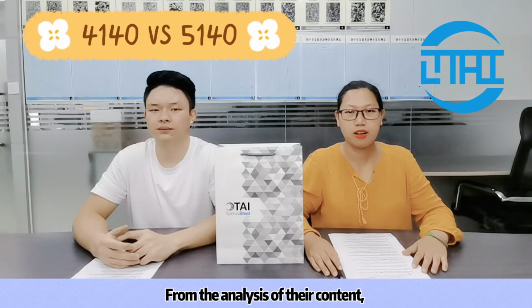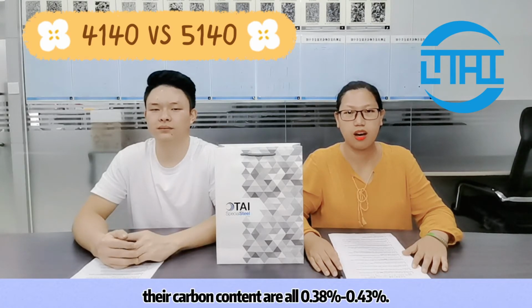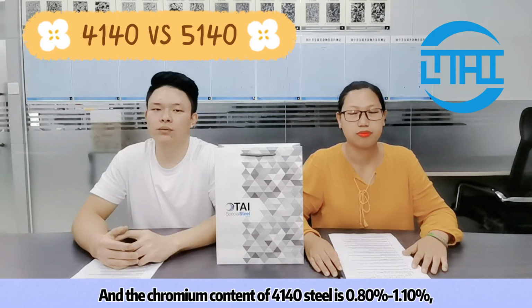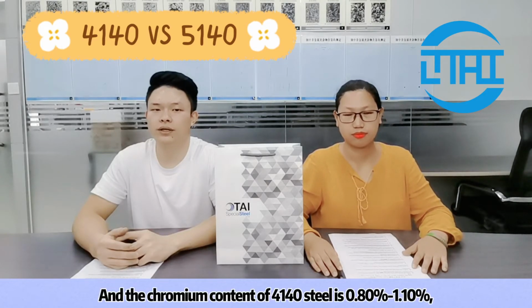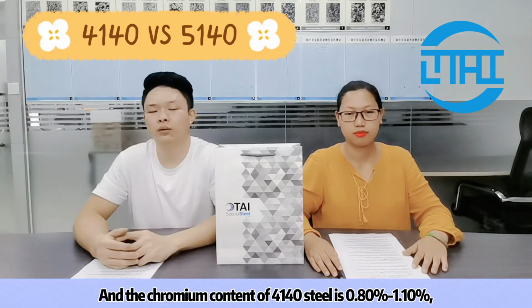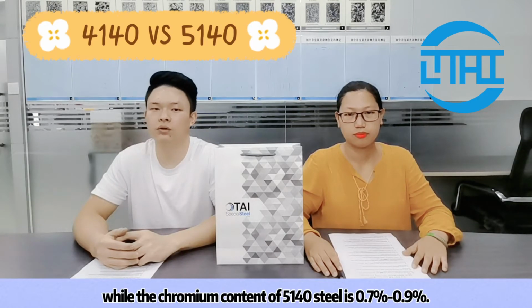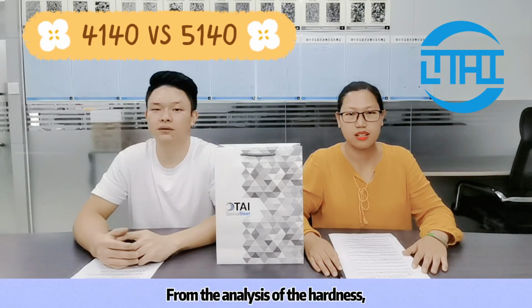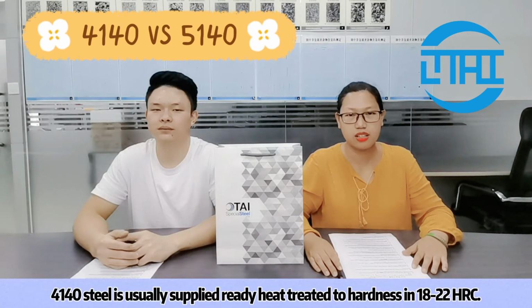From the analysis of the content, the carbon content are all 0.38% to 0.43%. And the chromium content of the 4140 steel is 0.8 to 1.1%, while the chromium content of 5140 steel is 0.7 to 0.9%. From the analysis of the hardness, 4140 steel is usually supplied ready heat-treated to hardness in 18 to 22 HRC.